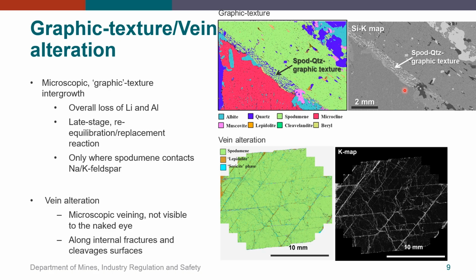The two bottom images show an example of the almost ubiquitous vein alteration observed in spodumene. Such veining is generally not visible to the naked eye and in the mineral map is variably identified as a mixture of secondary micas, lepidolites and so on, which can be described as sericitic in nature. The distribution of the vein network is more clearly shown in the potassium distribution map, shown here, which shows that veining mainly occurs along cleavage planes and fracture surfaces.